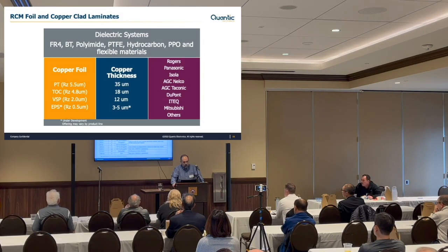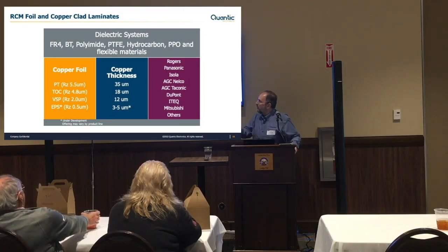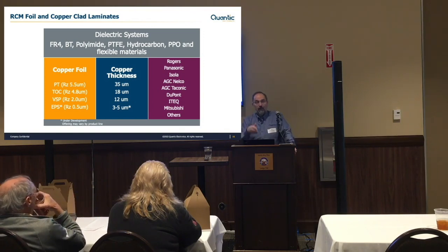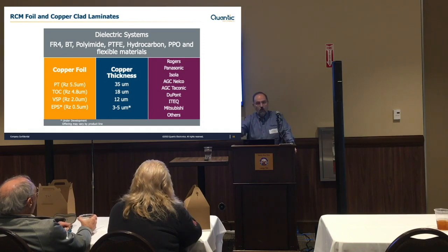And then we have this really high resistance material that's only available through one process. You can see there's a lot of overlap, where it says TCR and Ohmega apply. They can be supplied by either product, but some of them are only supplied by one. The very low ohmic value is supplied only by Ohmega, and the very high is only supplied by the Ticer TCR because of the process.